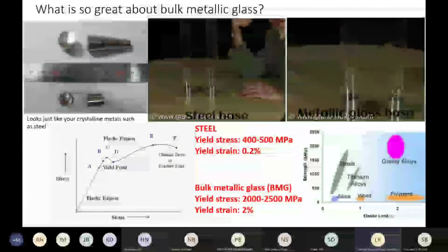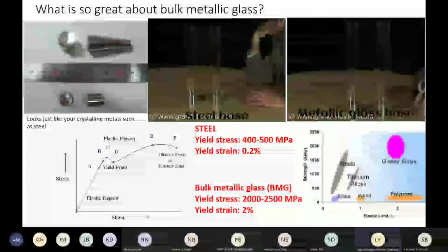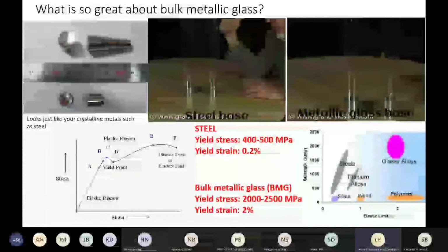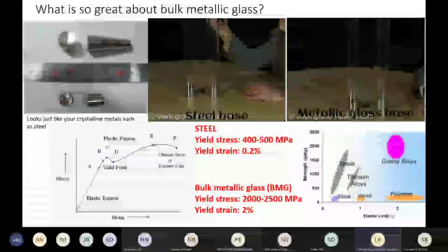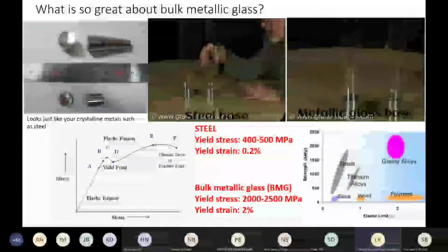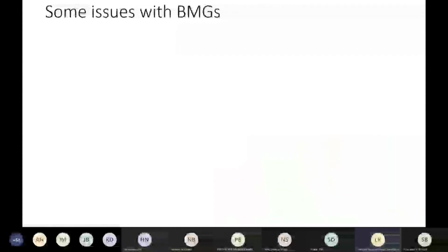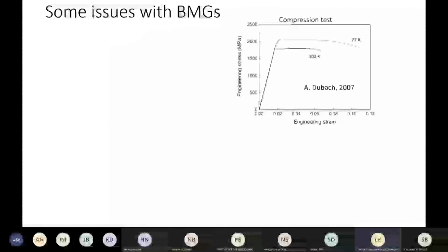If you look at all the materials in a curve where we compare the strength and elastic limit, as you can see, metals typically have higher strength but lower elastic limit. Whereas metallic glasses, you will see they have both high strength and high elastic limits. This is known as an Ashby chart, and we will look at some more as we go ahead. There are some issues with BMGs as well, and we will look at them.